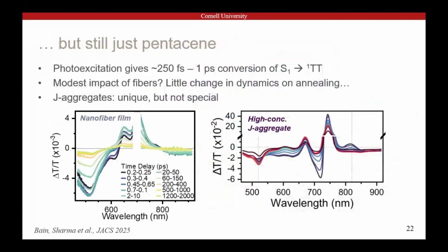But the terrible news was that every single one of these motifs that we studied does the same thing, which is what pentacene always does. It's going to fizz, but it does it in the normal way. In every one of these aggregate types, we start in the singlet state, and that decays to form triplet pairs on a typical pentacene timescale of femtoseconds to picoseconds. So we found some really cool structures, found ways to engineer the packing of pentacenes, but it didn't give us what we wanted.